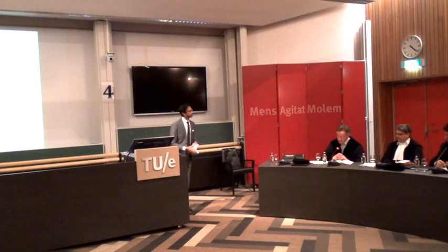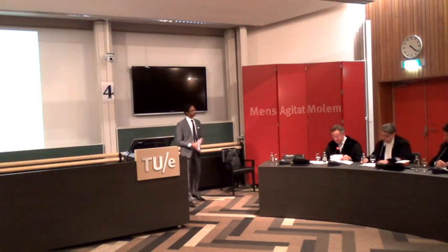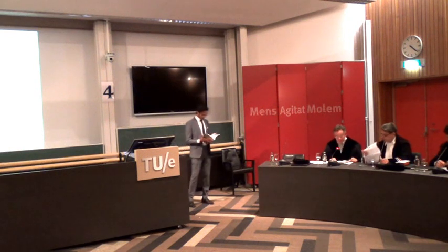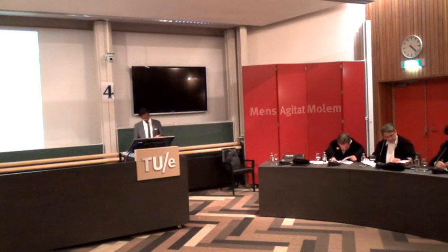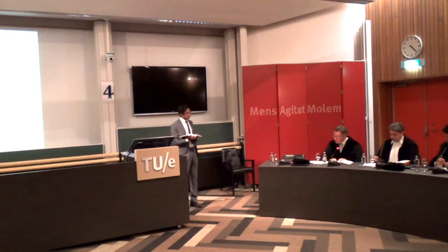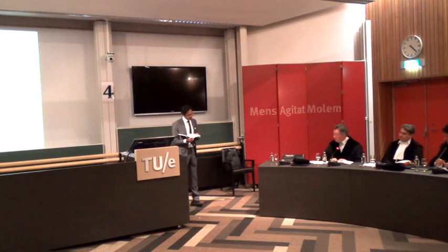Okay. I was thinking of something different because you measure the packing densities of the carbon nanotubes, displayed in figure 4.4. My argument would have been that since it is the excluded volume of the randomly oriented tubes that determines the packing density, and realizing that the excluded volume of a thin rod is the diameter times the length squared, I thought that was the reason for using the weighted average, because of the length squared in the excluded volume. Would you agree with that?